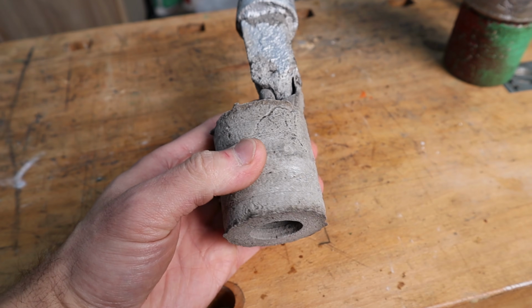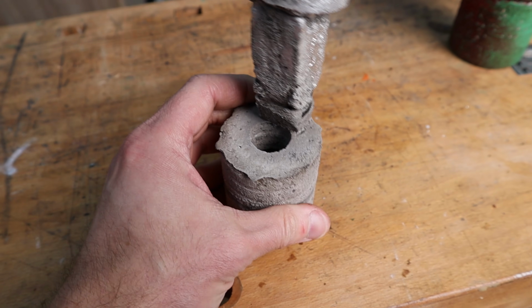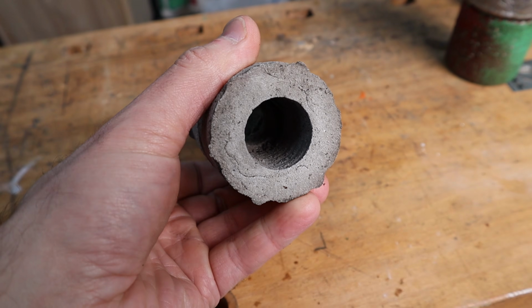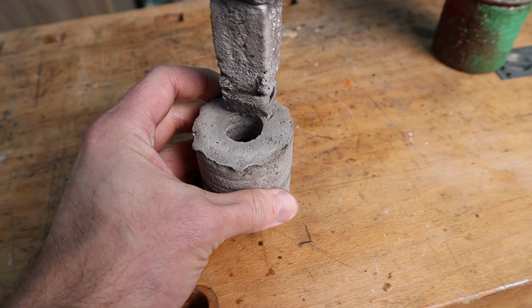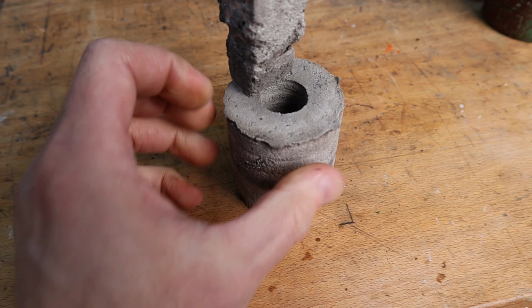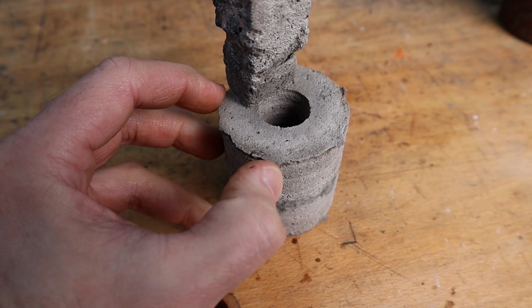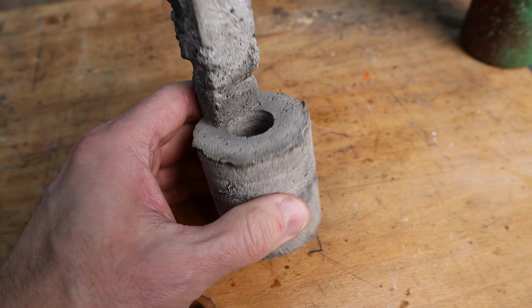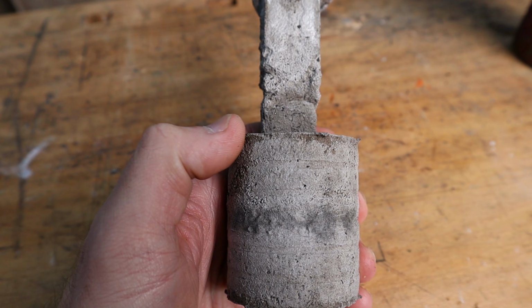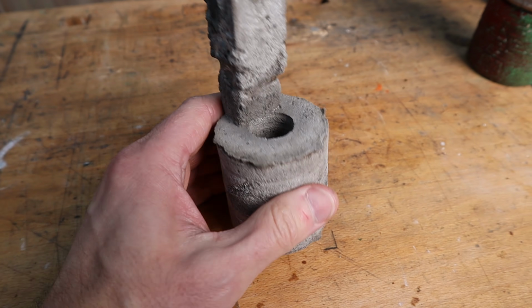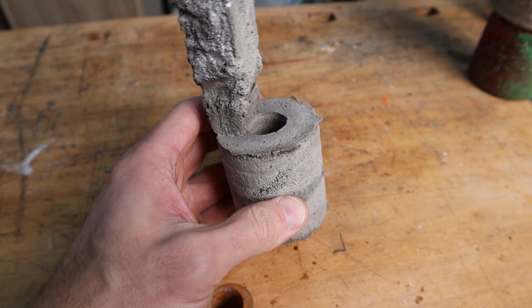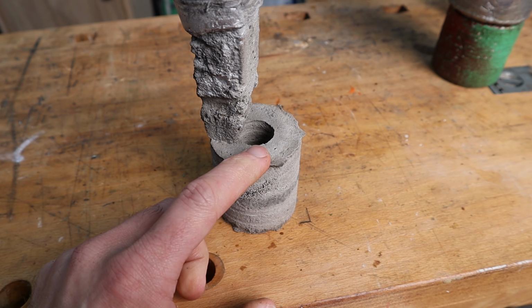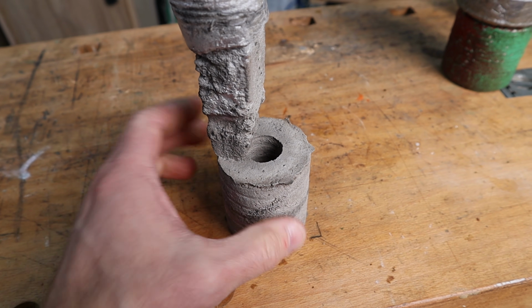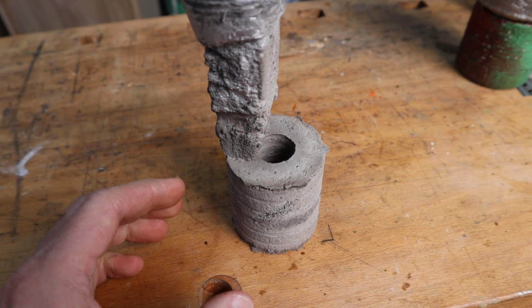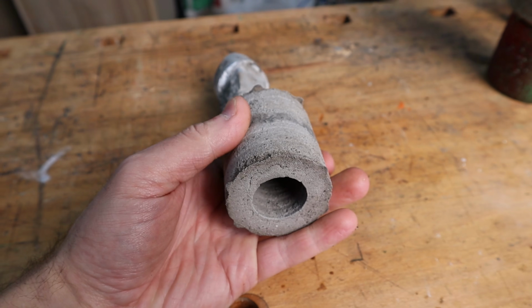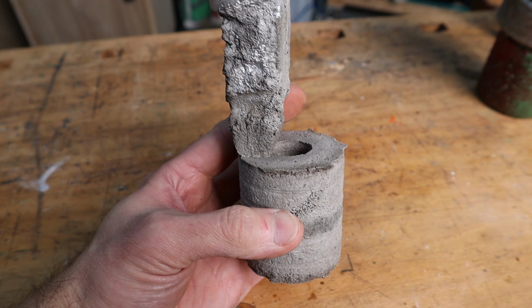So then we have this proper lost foam, and it looks kind of awful, but I actually think that it's perfectly usable. It's oversized in all directions. You can actually even see that it captured some of the tabbing when I cut the foam on the CNC machine. I see these tabs that are remaining. So it was able to preserve quite a bit of the detail, and I think if I chose to use the XPS foam, the pink foam, which I think will have a little bit more detail than the regular white polystyrene, I think it would have produced better results too.